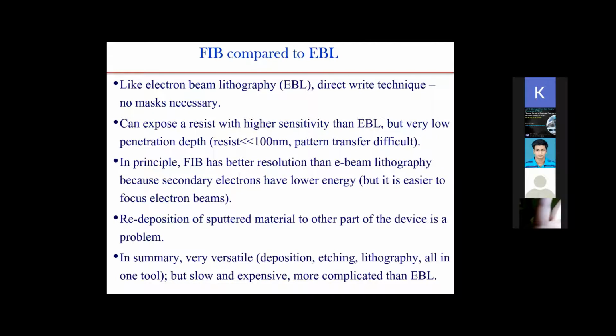Now this is also, like electron beam lithography, a direct write technique, so no mask is required. You can also expose the resist like EBL. Obviously, it is not that you cannot have a resist and expose it with the ion beam, but the problem is it has a low penetration depth. So it cannot penetrate much in the case of a resist. Because of its high momentum, it will get scattered initially, and it will also damage easily. So it is difficult to have a good pattern transfer by using resist.